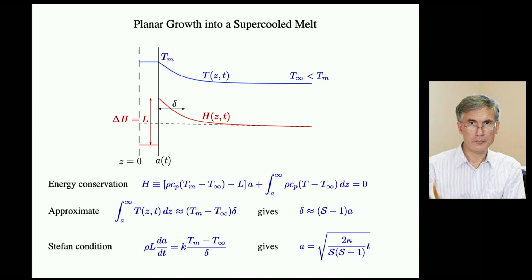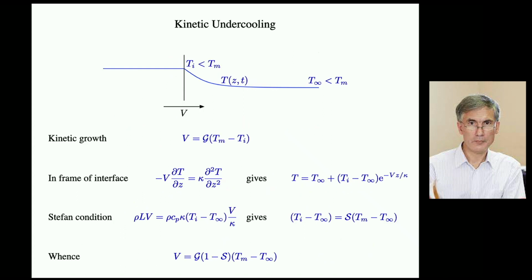And if our phase change is happening faster than that, we're really not in equilibrium. We really shouldn't be assuming that this interface is at the equilibrium freezing temperature. In order to advance, we need the rate of attachment, the rate of change of mobile liquid molecules into immobile solid molecules, to be more rapid than the opposite, than the ice turning into liquid. And in consequence, the interfacial temperature actually needs to be less than the equilibrium freezing temperature.